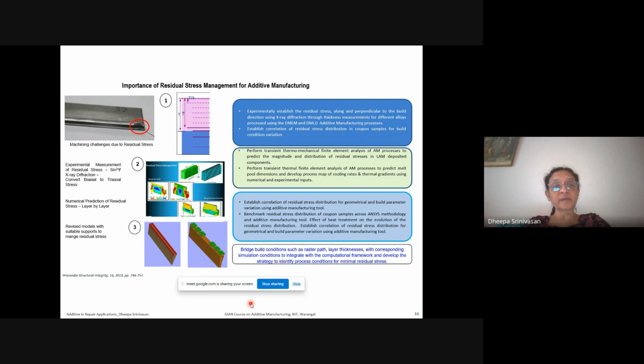So that's what I'm showing in the left hand side picture with the red colored circle. We measured the residual stress experimentally through the sine square psi technique using X-ray diffraction, and we also did some numerical calculations to overcome this, and then we incorporated a small design for additive manufacturing, such as these green colored struts here, so that when we are increasing the number of parts and we cut to remove the part from the build plate, we build these struts so that you can only cut these struts out.